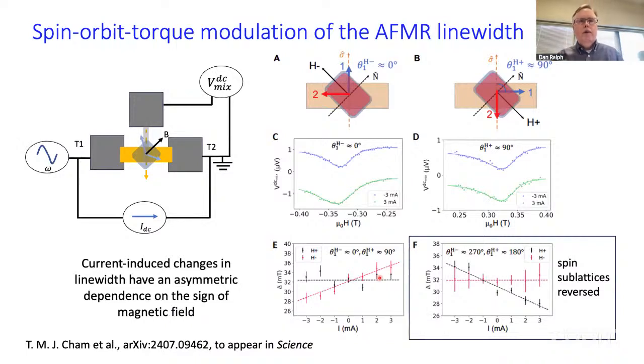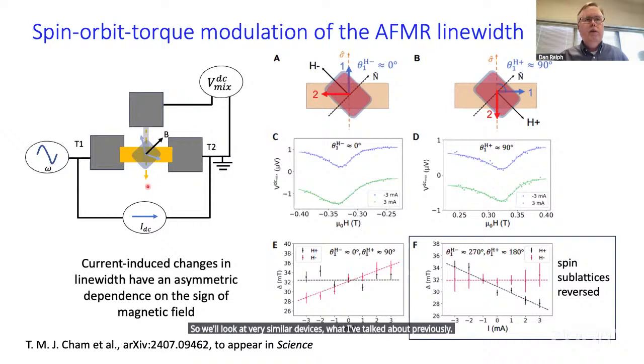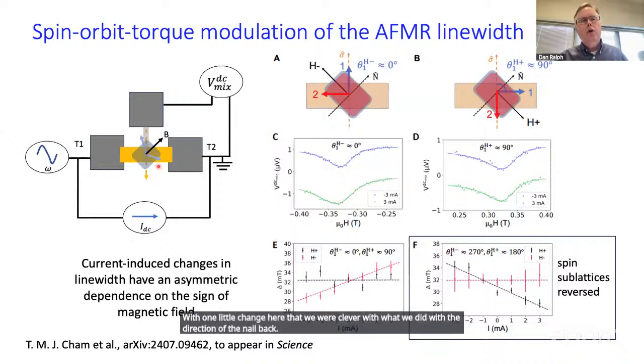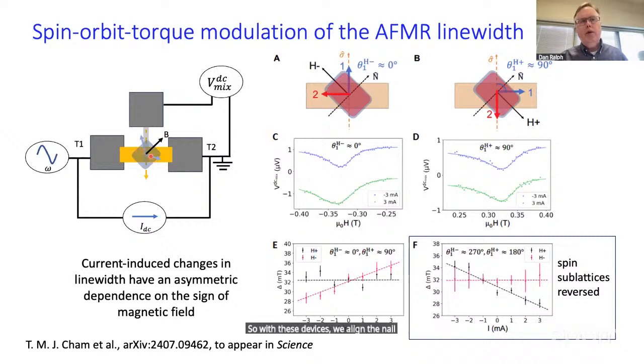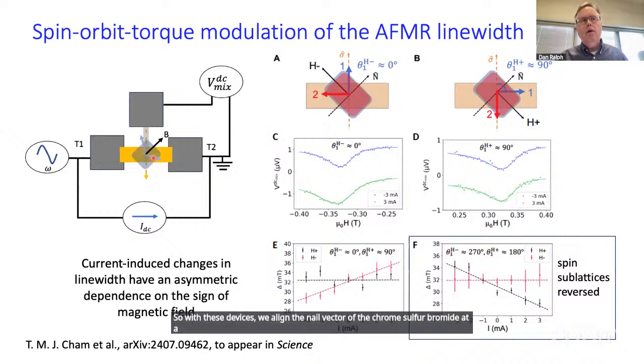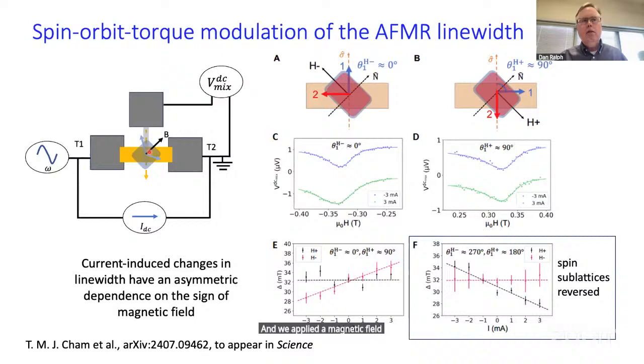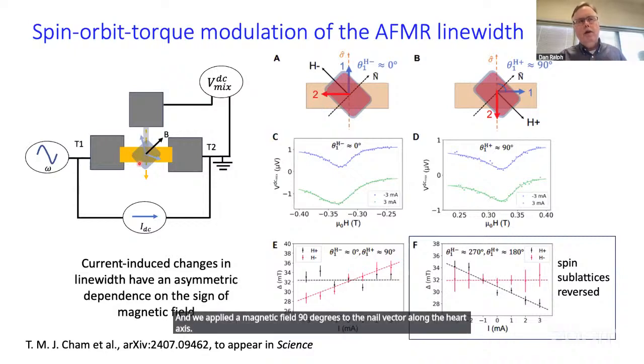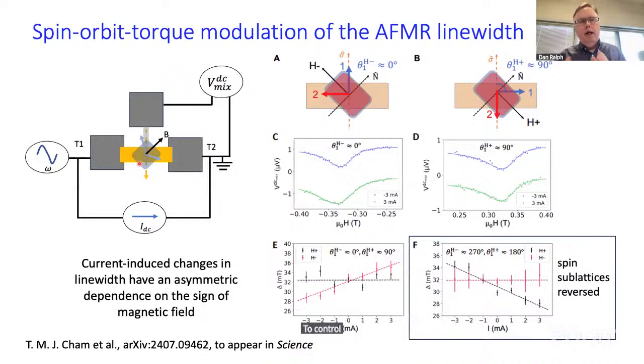So we'll look at very similar devices to what I've talked about previously, with one change here, where we were clever with the direction of the Néel vector. With these devices, we align the Néel vector of the chromium sulfur bromide at a 45-degree angle relative to the channel. And we applied a magnetic field 90 degrees to the Néel vector along the hard axis to control the offset angle between the spin sublattices.